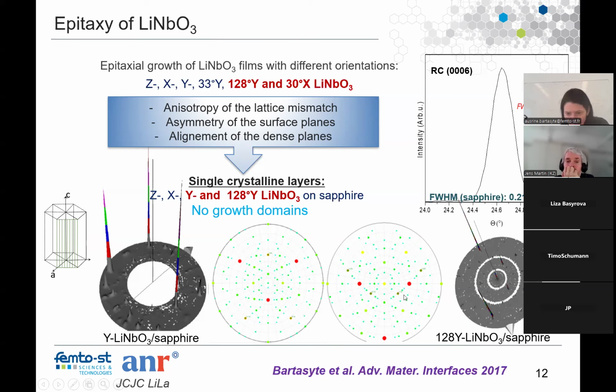So this was 104 planes with smaller dots. So we have 4 and 4 as expected. So, a nice rocking curve. Of course, I saw one paper that compared, saying, oh, we have a rocking curve of 0.04 and others had 0.25. Be careful about the precision or resolution of your diffractometer. So look at the substrate rocking curve. In our case, the rocking curve of the substrate is 0.21, so it means this is the resolution of the diffractometer. So we need to compare comparable things, and not just say, oh, my rocking curve is this, and another one was like 10 times bigger, because the resolution of the diffractometer was worse.